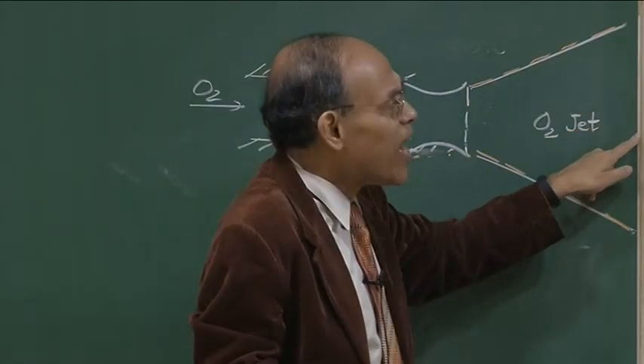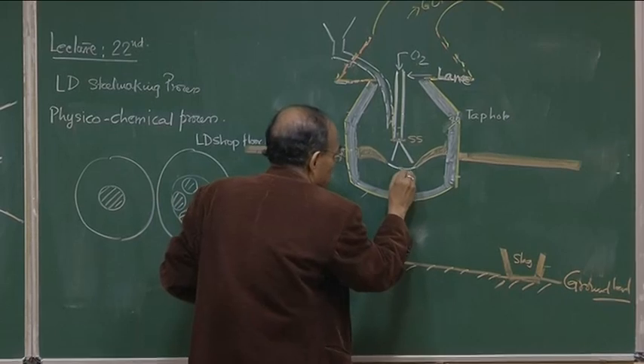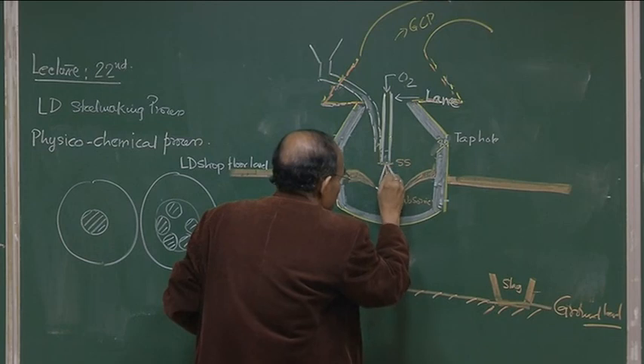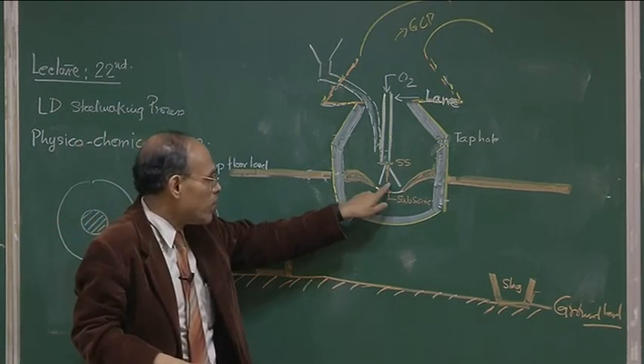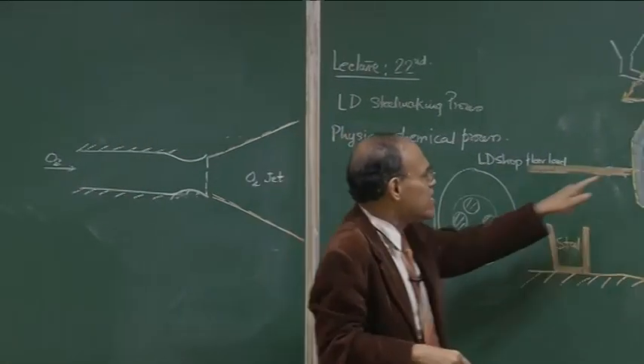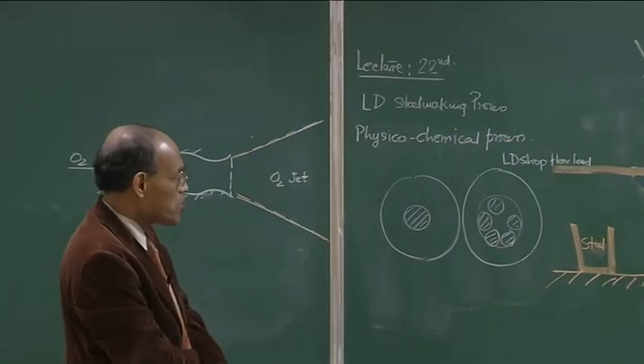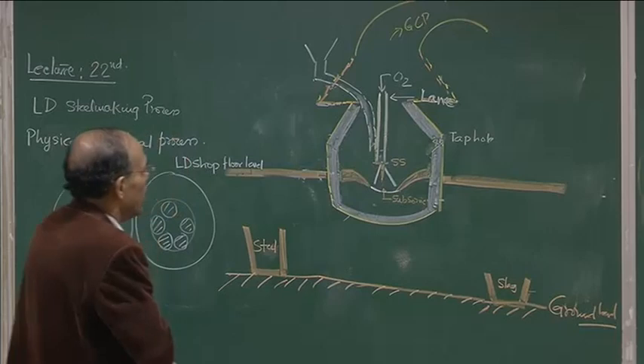So the jet, if it is supersonic here, at this impact region the jet is going to be subsonic, although there is a supersonic core of the jet. The center one, the red one that we have drawn here, is a supersonic core, but by the time it impacts the metal, unless the jet is very close to the surface, the metal sees a subsonic jet striking. But that itself is maybe 0.5, 0.6 Mach number, so it is quite an intense jet that strikes the surface with quite intense actual momentum.